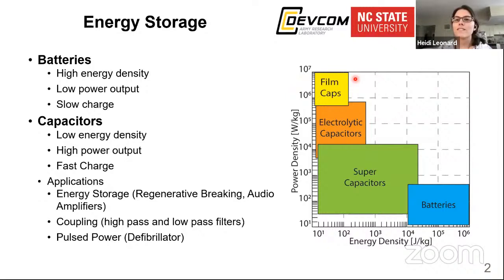Right. I wonder if the different porosities affect how you deposit your alumina and hafnia, or do you know if that's a factor? It's known with atomic layer deposition that as much as ALD can coat really complex structures, you are limited in how complex based on the precursor materials you use. We believe it won't be a problem with the aluminum precursor or the hafnia precursor in coating our metal foams completely, even a really dense metal foam. That's just the nature of the precursors, but that wouldn't be true with all ALD growths, with all the precursor materials you could choose from.